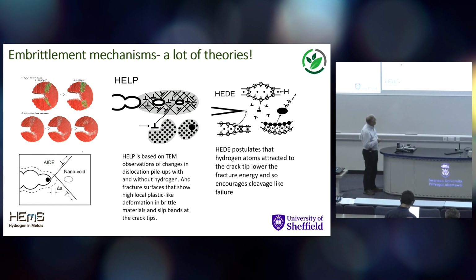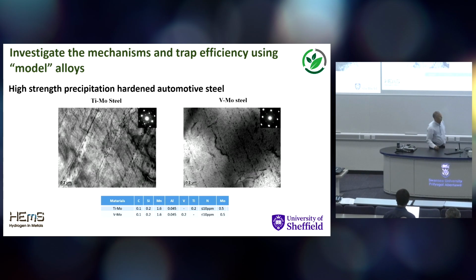HEDE, which is another popular one, simply postulates the hydrogen goes to a crack tip and breaks the atomic bonds there, changes the bond energy, the cohesive energy there, and the cracks can propagate through. There's one called AIDE, or however you pronounce it, which is similar to HELP, but it has very important differences you should understand, and there are more modern theories based on atomistic modelling, which I'll come across again a bit later.